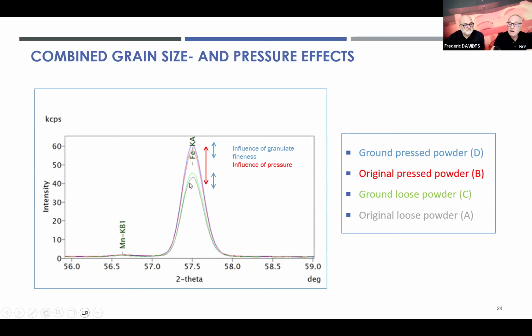And when we look at the ground pressed sample, we see here about 60 kcps. So it's a difference of 20 kcps or 50% for the same sample that contains the same amount of iron. Yeah. So we can all see the difference here.